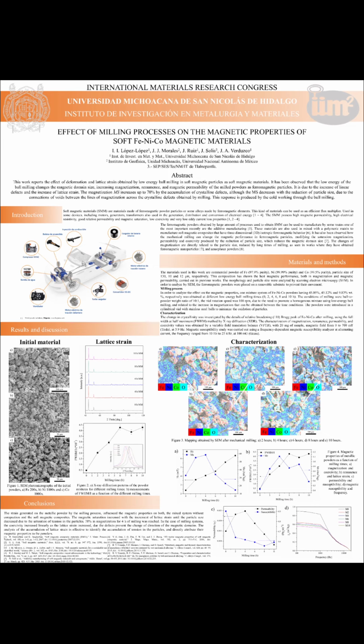In this work, the microstructural and magnetic characterization of soft magnetic iron, nickel, cobalt material were investigated. In order to carry out our study, powders of these elements were first mechanically milled under different conditions to obtain different shapes and particle sizes, which induced deformation and lattice strain, leading to the enhancement of the magnetic properties. In this way, any change in the magnetic behavior due to the milling process can be measured, to obtain soft magnetic materials with high magnetization compared with the starting systems without deformation, also improving the remanence, magnetic permeability, and electrical resistivity just by increasing the lattice strain and defect density.